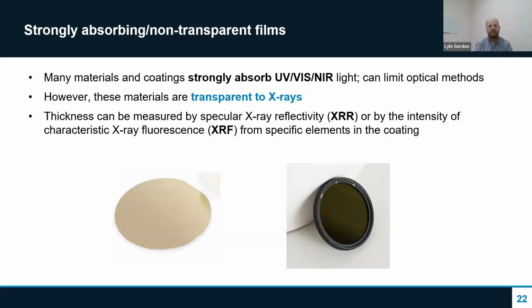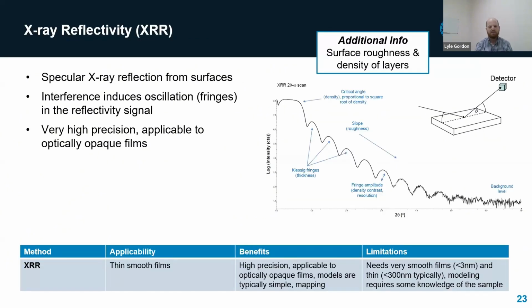So like we discussed, many materials, particularly metals, can absorb light, and this limits the ability of optical methods to probe the thickness. However, for pretty much most of these materials over the relevant thickness range, they're somewhat transparent to X-rays. So we can use X-ray reflectivity or X-ray fluorescence, looking at specific elements to determine the thickness of the coatings. So I'll tell you a little bit about X-ray reflectivity.